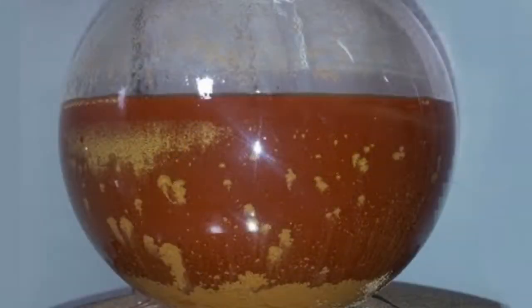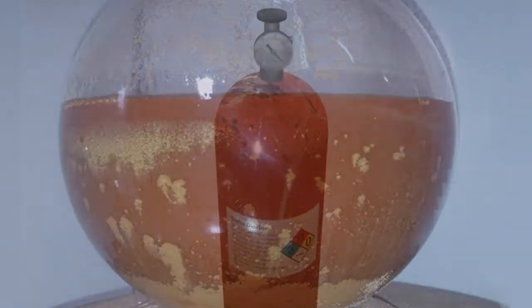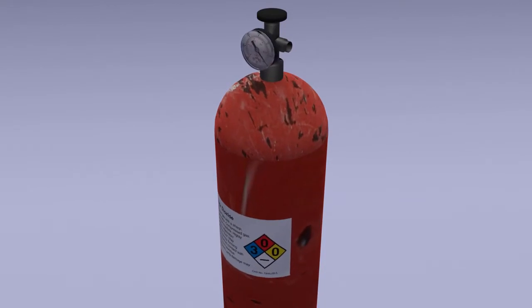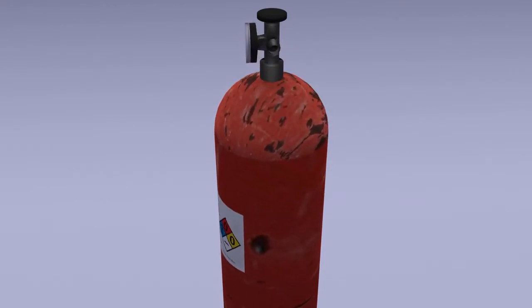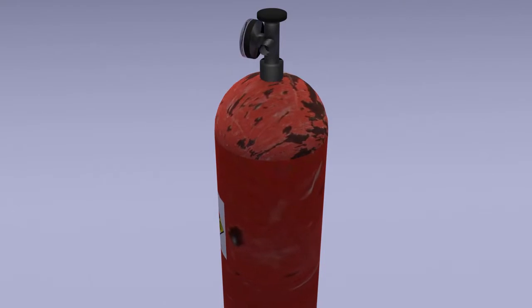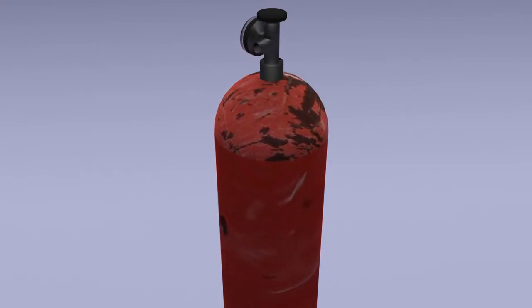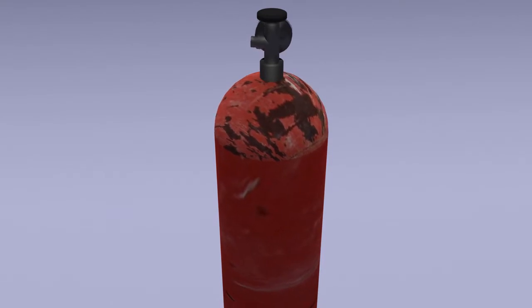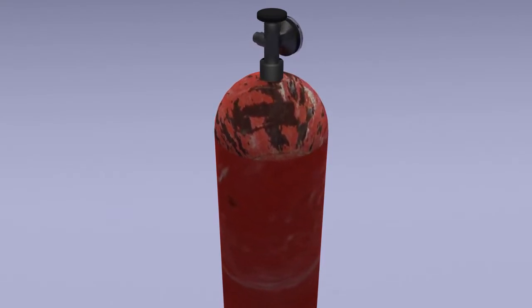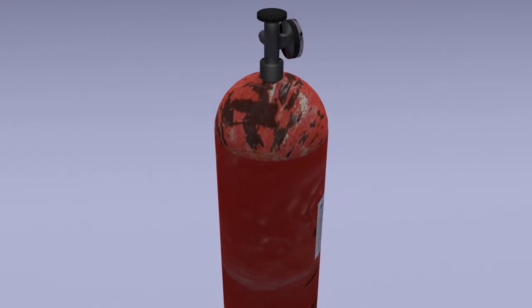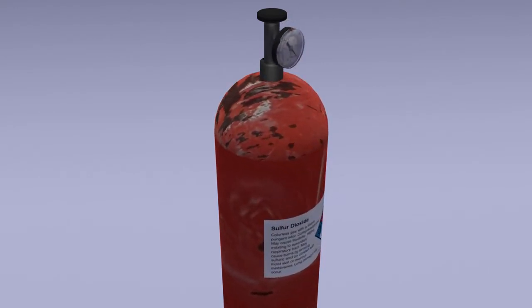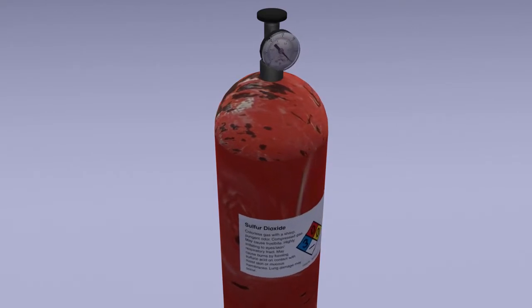There are two different precipitants that are traditionally used. For large-scale refining, sulfur dioxide gas is the traditional choice. This is both very corrosive and very toxic. Surprisingly, this is actually a good choice for large-scale refining because large-scale refiners have the hoods, ventilation, and scrubbers to handle this gas, and because the sulfur dioxide produces heavy gold particles that are easily filtered.